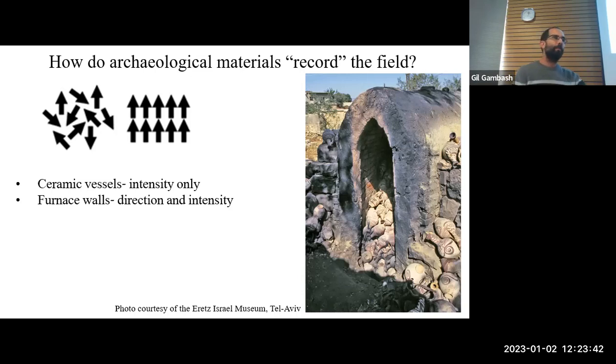So if you take any mud from any archaeological excavation, you might have these ferromagnetic minerals, but they'll be oriented this way, the magnetic signal will be in this direction, one in that direction, and the total magnetic signal will be very weak and not unified. But once you heat it up above a certain temperature, they're all aligned with the magnetic field. And then when they cool down, they'll be aligned this way. Of course, it doesn't have to be exactly like this, but statistically, they'll all point in the same direction. And then we can come thousands of years later and measure this magnetic field